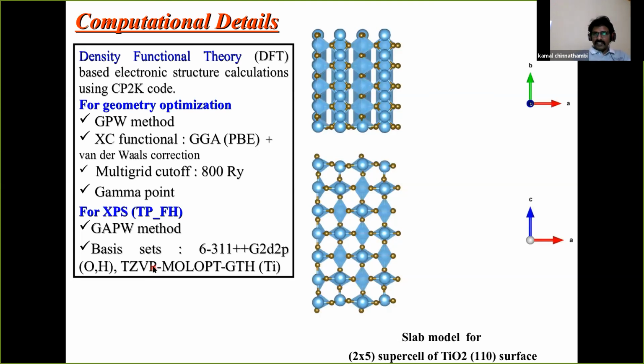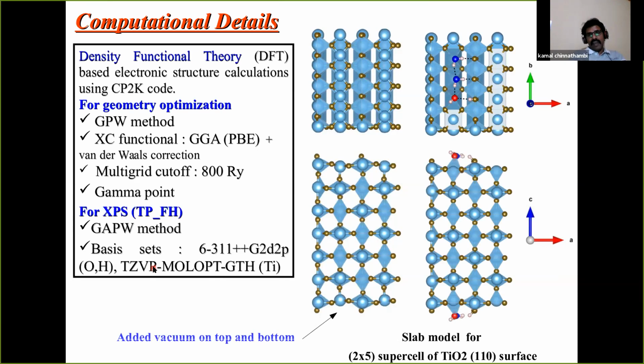It is not three-dimensional periodicity. We break the three-dimensional periodicity in one direction. For that purpose, we add a vacuum layer in one of the directions, so that when you apply the periodic boundary condition, the material is repeated in two directions, X and Y, but in the perpendicular direction, we have a vacuum. So it creates two surfaces, top and bottom, of this slab, on which we adsorb the molecules. We use a symmetric slab, meaning that the top and the bottom sides are mirror images. So this is the slab we use for our calculation. You can look at the top and side views of the slab.